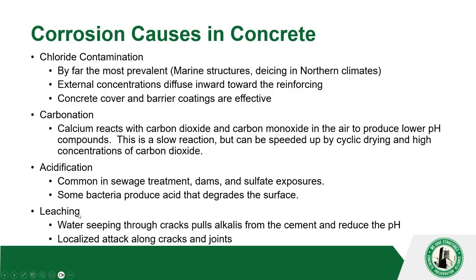And leaching, you do see in parking garages, especially along cracks on the roof. You see the top decks, and water goes through the cracks. It pulls the calcium out of the cracks. It creates little stalactites on the bottom of the slab, that efflorescence that people see. It pulls those alkalis out, and it lowers the pH. So it creates a localized attack along the cracks in the joints, just like carbonation would do along those cracks and joints.